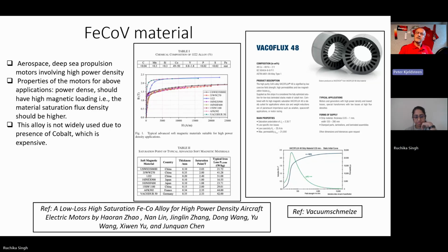But is it made in sheets as well, or how is this produced? I'm not very sure about the production of it, but I believe it's also like electrical steel sheets. If I can find some information: strip material thickness, forms of supply, so 0.05 to 1 mm, that's what the data sheet says, with 120 to 280 mm width. So yeah, electrical steel sheets of iron-cobalt-vanadium. So it's the same manufacturing method as the standard silicon laminated alloyed steel.